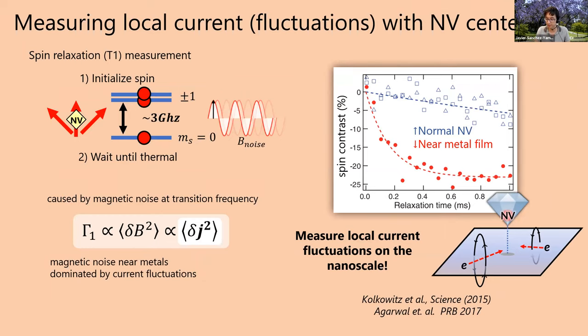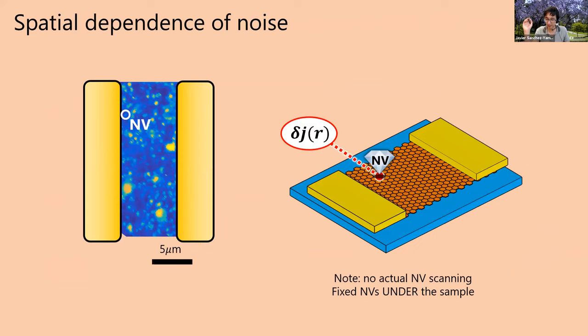All right, so let's look at the spatial dependence of the noise. So this is a NV center. This is a fluorescence map of the NV centers here. And we're gonna measure the magnetic relaxation rate, which is gonna tell us the current fluctuations in the graphene from this NV center, which is located like 50 nanometers away from the graphene. And I want to point out here that we're not scanning the NV centers. They're just a bunch of them sitting underneath the graphene device.